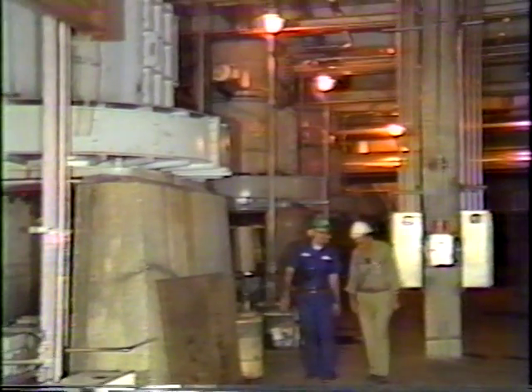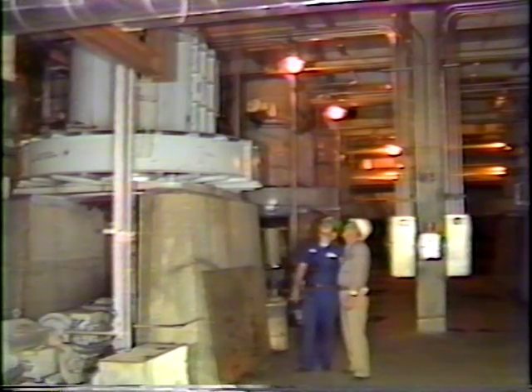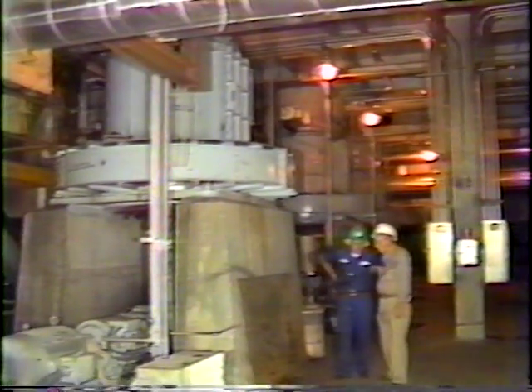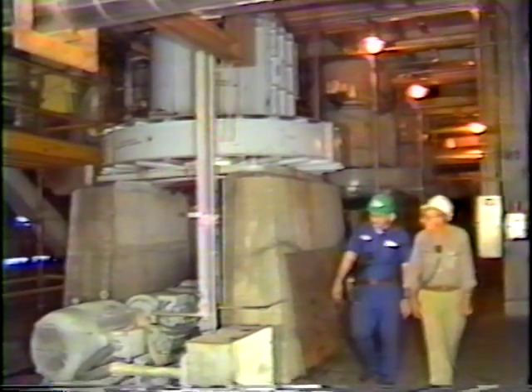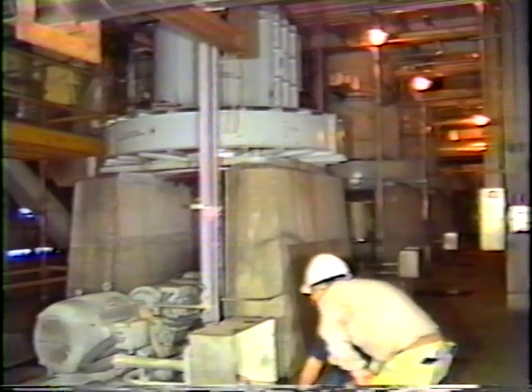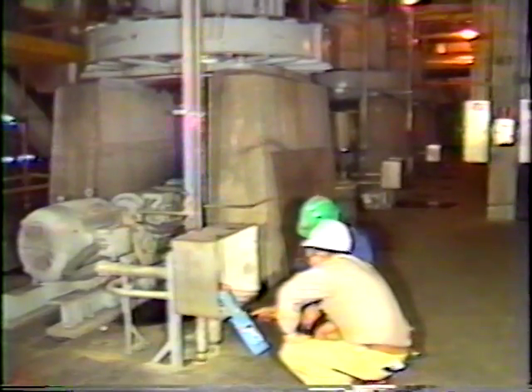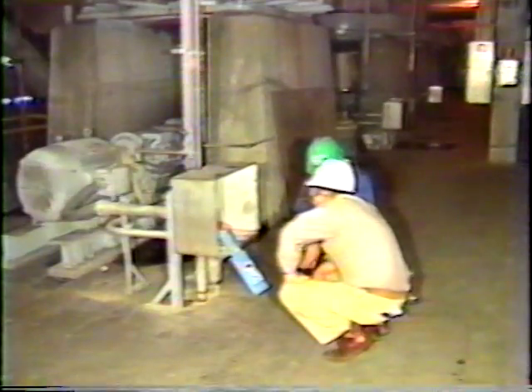This then constitutes an air-to-coal ratio of 1.7. Once ground to size, the coal is air swept out of the mill by air bustles or wind boxes that surround the bottom of the mill. At the present time, the coal fineness is being set and ground at 87% minus 200 mesh, and the capacity of each mill is 14,770 pounds of feed per hour. Full load amps on the 125 horsepower motor is 136 amps.